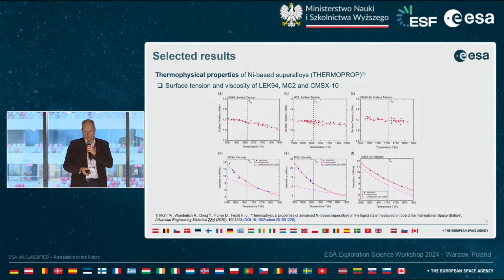and this dashed line that you see underneath is what has been predicted earlier by models for these alloys, so there's quite a significant difference. In particular, you see that for the LEK94 and the MC2 alloy, the difference is particularly large if you cross the liquidus line, which is this vertical dashed line, and go into the undercooled liquid range, so the models are not very accurate there.